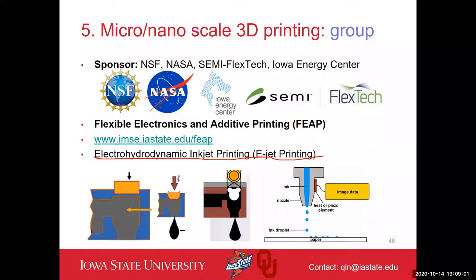The idea for e-jet printing is that for all printing techniques, we need to have a driving force to drive the material flow. The driving force can be gravity. It can be a piezo film to drive the material out from the nozzle. It can be a squeeze function to squeeze the ink out from the nozzle. The idea is to use a driving force to drive the ink out from a nozzle so that we can achieve droplet-based printing.